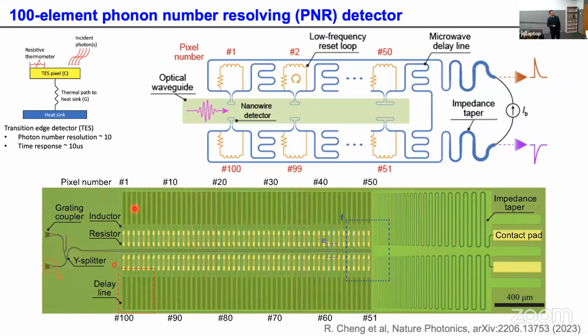So here's how this detector works. It looks pretty complicated, so I'll walk you through. In the middle is a waveguide made of silicon nitride, and we expand the waveguide adiabatically to make it wider. Now we can pattern a lot of individual nanowires over here. Those nanowires are connected through the blue trace, which is a transmission line made of niobium nitride. The nanowire is also niobium nitride, so the same material. The light velocity in this transmission line is reduced by a factor of 100 compared to the velocity of light in the waveguide. When a photon lands on one of the detectors, it sends a pulse in opposite directions. Those pulses propagate to the impedance transformer, going to 50 ohm. You register 2 pulses, measure the arrival time difference, and you can infer which detector flashed.